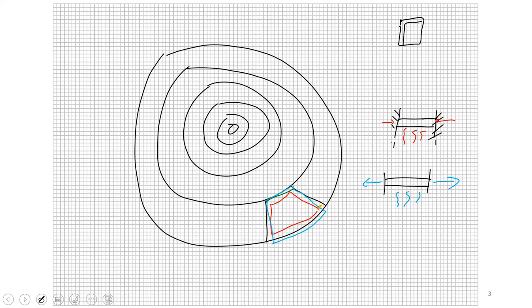It's the whole growth ring around the tree that is shrinking at the same rate approximately. So it's able to shrink just fine with its neighbors to the left and to the right along the growth ring. However, look here. At this location here, there's a difference. It would like to be where the red line is, but in fact, it's stuck at the blue line position because this inner ring hasn't shrunk down yet, and it hasn't shrunk because its moisture content hasn't really decreased much.